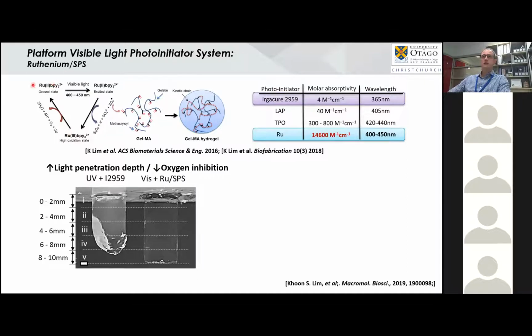Essentially, if you have a ruthenium and sodium persulfate based metal complex system, then under excitation with light in the 400 to 450 nanometer range, you get excitation and oxidation of ruthenium. That then generates sulfate radicals, which can then drive a chain growth polymerization of your hydrogel. In this example, that is gelatin methacryloyl. So that is a mechanism for radical-based polymerization.